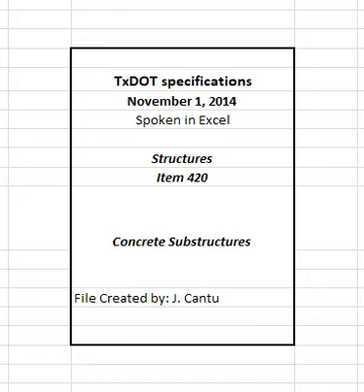Wet the existing concrete by ponding water on the surface for 24 hours before placing subsequent concrete. Use high-pressure water blasting if ponding is not possible to achieve SSD conditions 15 to 30 minutes before placing the concrete. An SSD condition is achieved when the surface remains damp when exposed to sunlight for 15 minutes. Draw forms tight against the existing concrete to avoid mortar loss and offsets at joints. Bonding agents are not required unless indicated otherwise.